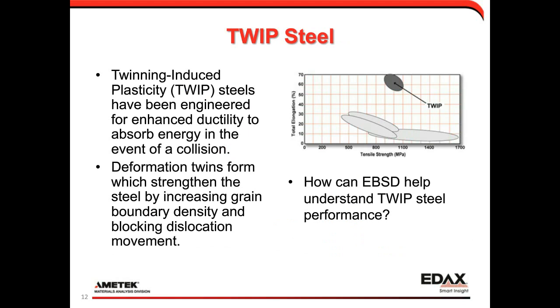The first example I want to show is what's termed a TWIP steel, or a twinning-induced plasticity steel, a class of alloys that have been engineered to enhance ductility to help absorb energy in an automotive application in the event of a crash. If we look at the chart on the top right, it gives an idea of the property curve relative to traditional steel alloys: the TWIP steel is an area where it has higher strength and higher ductility relative to other alloy classes. This occurs through the formation of deformation twins as a material is strained. It increases grain boundary density, and it blocks further dislocation movement. So the question is, how can EBSD help understand TWIP steel development and performance?